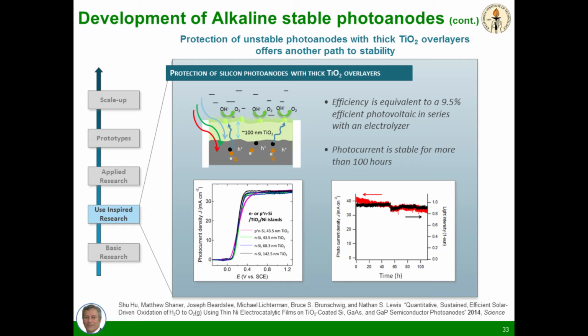Now, Chris Chidsey and Paul McIntyre had done this by atomic layer deposition a year or two earlier with TiO2 in a very thin nanometer layer tunneling barrier, but they found the thicker layers, in the way they made it, blocked electrons. We wanted to use thick protective films in order to get conformality and robustness, and found that they passed electrons and let silicon, which was oxidatively susceptible, oxidize water to molecular oxygen photochemically for hundreds of hours.